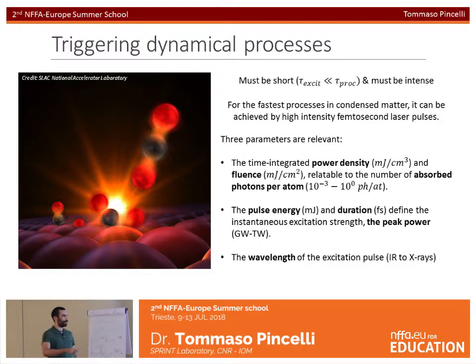For the excitation, there are three parameters that are relevant. So the time integrated power density, so how many photons per atom, after all, we are sending onto our sample. And so the important terms are the volume power density, which is measured in millijoules per centimeter cubed, the fluence, that is the areal density of power, that is measured in millijoules per centimeter square, and the number of absorbed photons per atom, which can be calculated from the absorption coefficient.